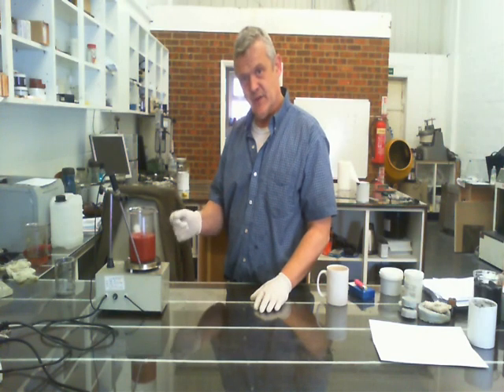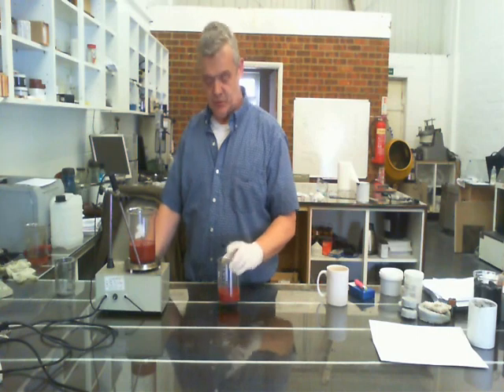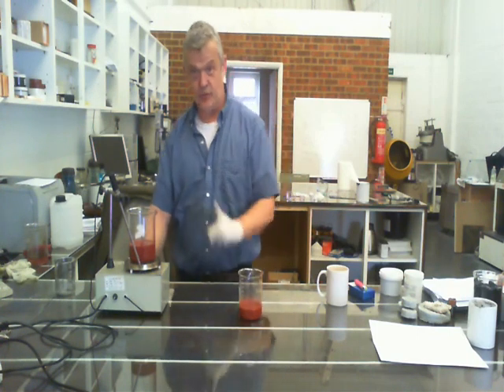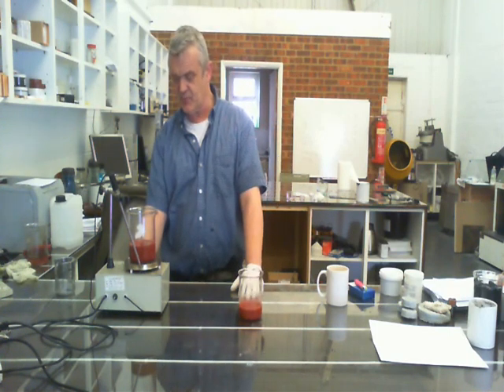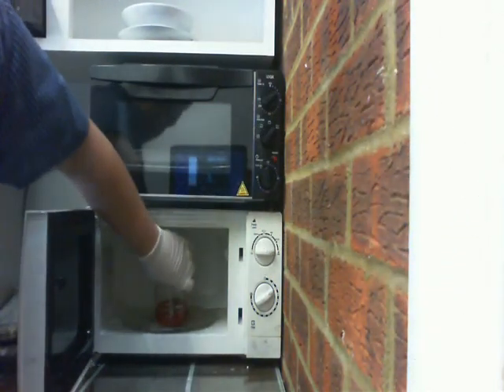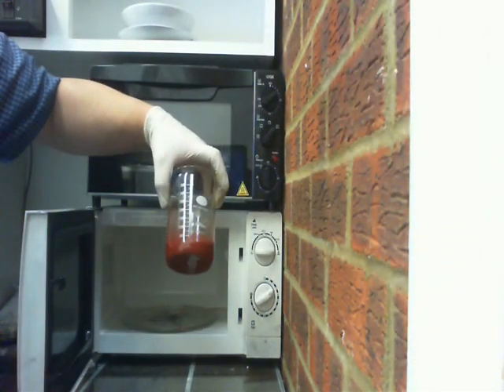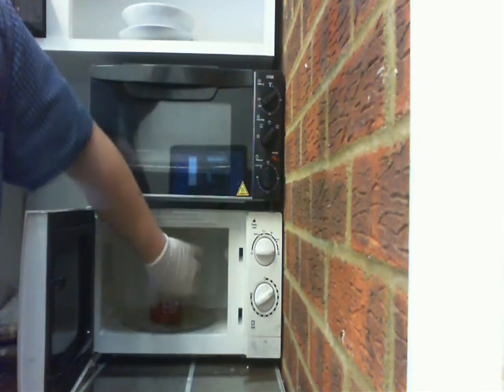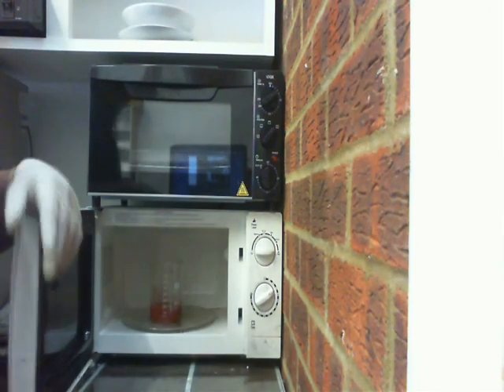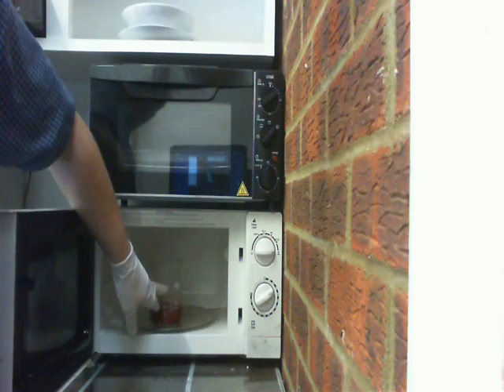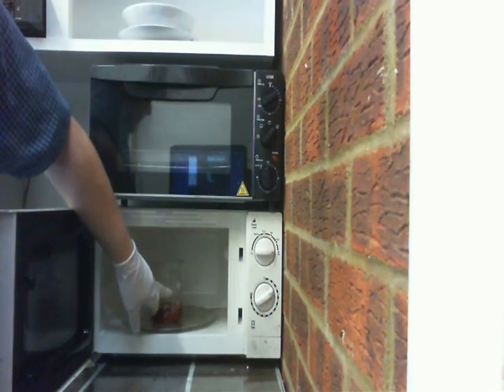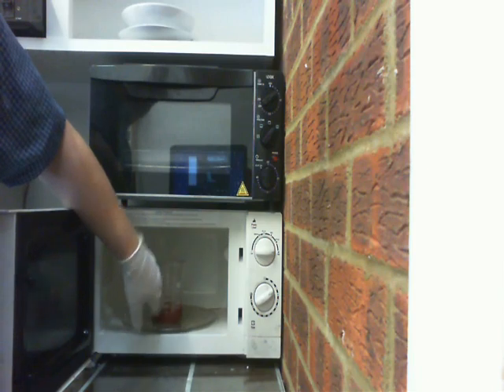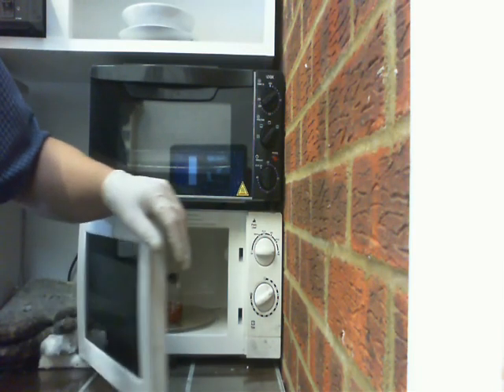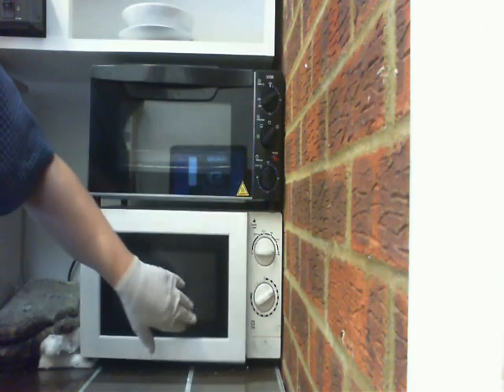But what we're going to do now is take it and put it in the microwave. So I've poured off 75 millilitres for the microwave. One thing I forgot to mention was that you need to change the temperature of this from 50 up to 90. So you put this at 90 degrees centigrade. So here are our copper nanoparticle, here is our copper oxide in formic acid and 10% gelatin solution. Pop it into the microwave at high for a few minutes. What you'll see happen is it will bubble up, and it'll bubble up to about here. But because of the gelatin in there, it won't go any further. And that means that we can leave that in there for as long as we like until that red turns into pink.